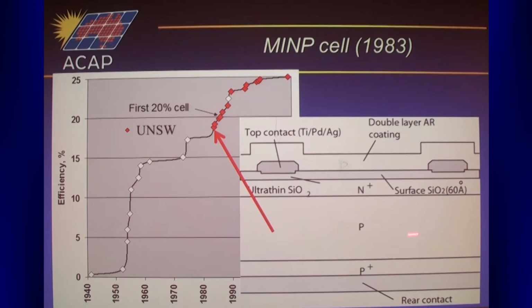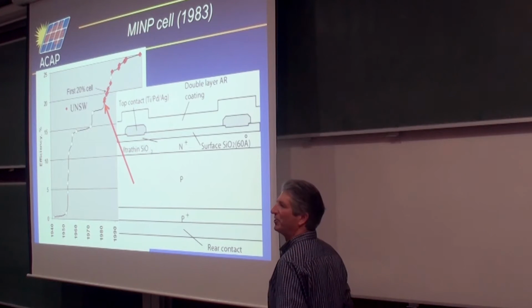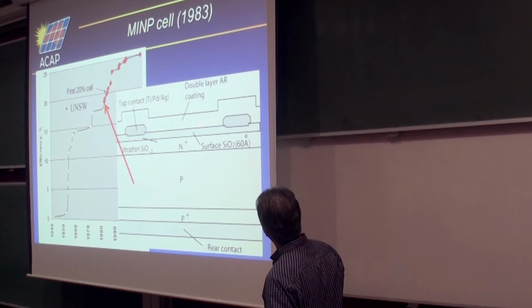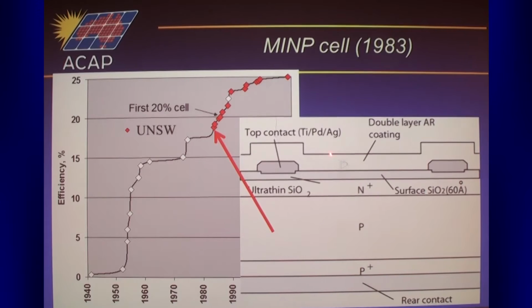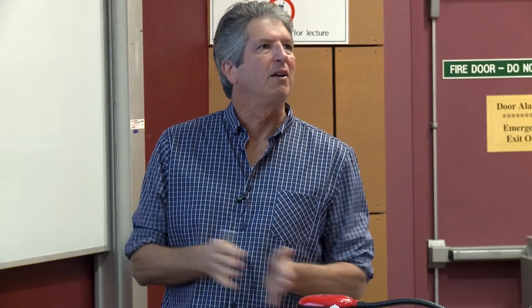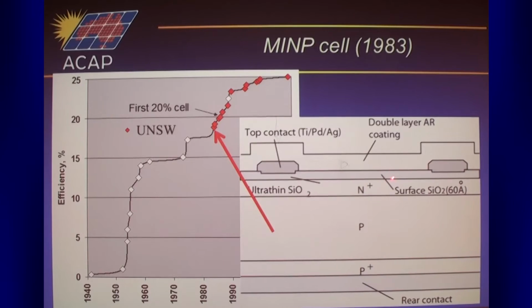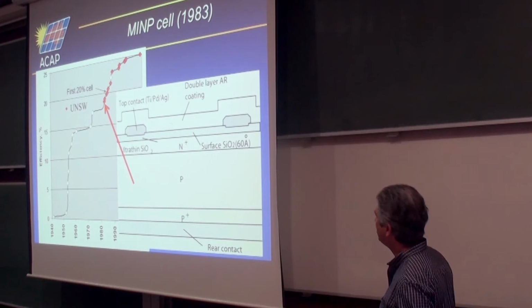The silicon index is very high, it's about 3.5 relative refractive index. That of oxide is about 1.4, 1.5. So it turns out optically you want a gradation in index going from silicon to air to get the lowest possible reflection. So having a low index layer in the stack isn't a good idea. So these anti-reflection coating materials that we chose were progressive; we had a double layer coating, one layer that was high index, zinc sulfide, and then another layer of magnesium fluoride to try and grade the index of silicon down to air. Having this oxide in the way wrecks the optical design, but if you keep it very much smaller than a wavelength, the light doesn't really see it. So here we had different constraints on how thick we could make the oxide. It was about 3 times thicker than in this region, just keeping it so it didn't influence the optics.